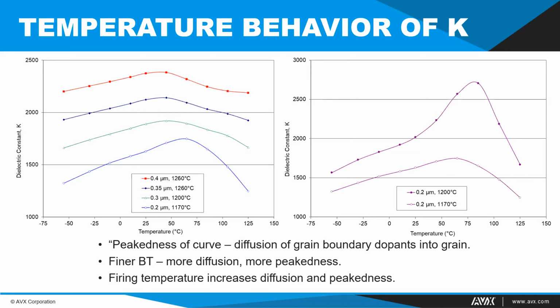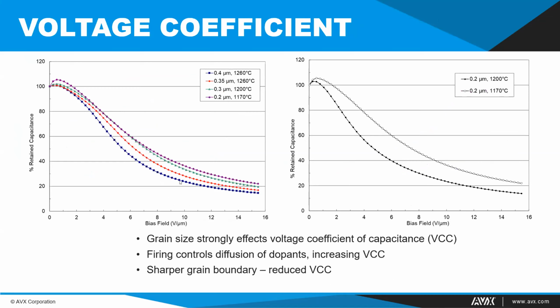Let's see here. We can also look and see the same kind of changes in the voltage coefficient. If we look through these materials here, we can see that the steepness of this curve tells us something about the voltage coefficient of the material. A steeper curve will have more change with voltage than a shallower curve. And you can see that some of the largest grain materials, as we might have pointed out, do have the largest change in retained capacitance or dielectric constant with biasing field.